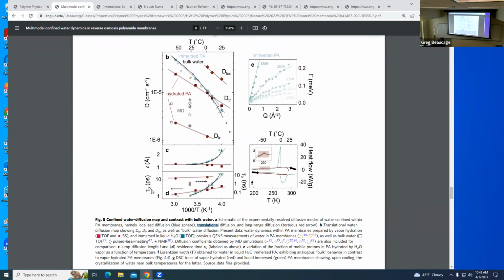So the taus for these, some of the taus go with one technique, the nanosecond, the other with the picosecond. So this is backscatter and time of flight. So there's two scales for the things, and then these couple, so the symbols match up. So the localized one, the relaxation time should be an Arrhenius behavior. So it should be log of that versus this. This one's not supposed to be Arrhenius, I don't think, but anyway, he shows it's Arrhenius.